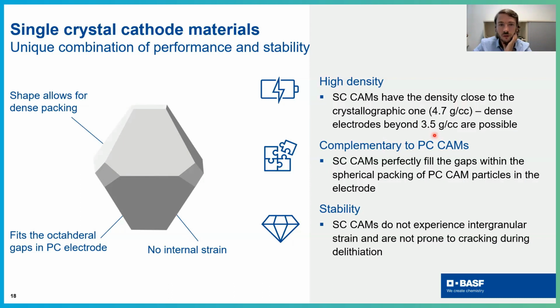The cell manufacturers require at least 3.5 grams per cubic centimeter electrode density, and I have to say that it is actually impossible to achieve it with only polycrystalline samples, even if you tune the particle size distribution, use bimodal systems and everything. So you need at least a component which is single crystalline, to fill the gaps of your polycrystalline electrodes to increase the density. Otherwise, it's just not possible. And this is also interesting: in the polycrystalline electrode, you have just closed sphere packing, right? And there you have gaps up to 30% of your volume. And these gaps are either tetrahedral or octahedral.